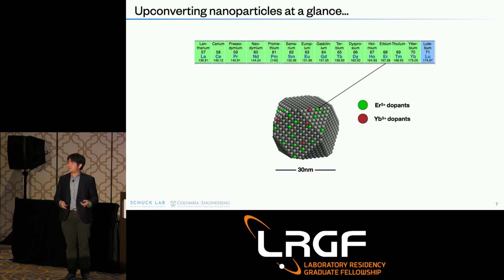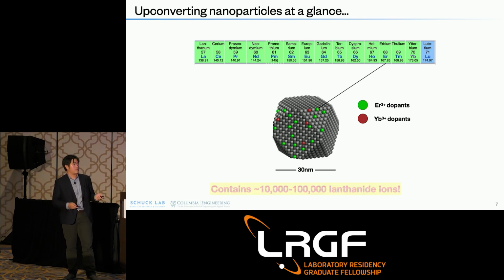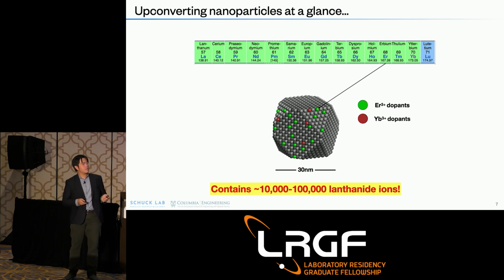And upconversion physics was something I've been studying throughout my PhD, as well as in my LRGF residency at Los Alamos. So this is physically what an upconverting nanoparticle is. It is a nanoparticle about 30 nanometers in dimensions. They're ceramic, but they're doped with about 10,000 to about 100,000 of these lanthanide dopants. And this is what really makes upconversion happen.